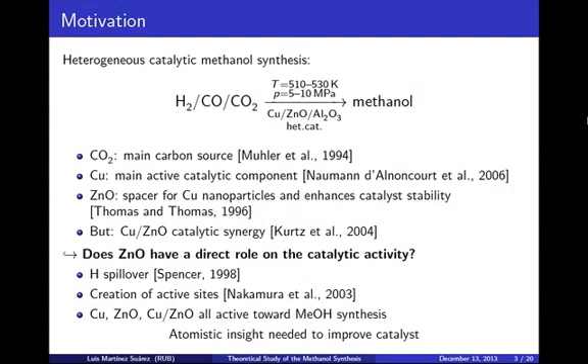So, does zinc oxide play a role in the reaction mechanism? It was proposed, for instance, that zinc oxide provides hydrogen atoms for the copper active sites, or that it aids in the creation of special active sites. In addition, copper and zinc oxide separately also present activity toward methanol synthesis, although to a lesser extent.